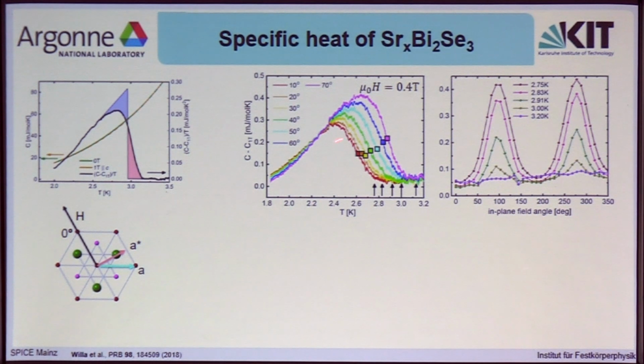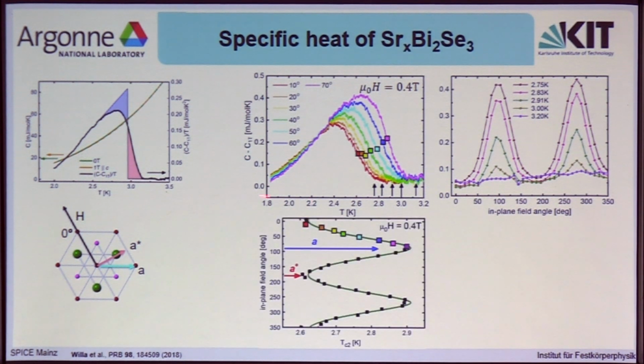You can also look at it differently. You can also take the superconducting transition temperature, here it's simply done by the midpoint of the transition, and you plot this as a function of field angle. And also here, you can see for the full rotation of the field in the plane, you see this nice twofold anisotropy. Now, as has been pointed out by previous studies, and I will come to the assignment later, just to make the assignment clear here, we will call the maximum here of the TC along the a-axis and the minimum along the a-star axis.